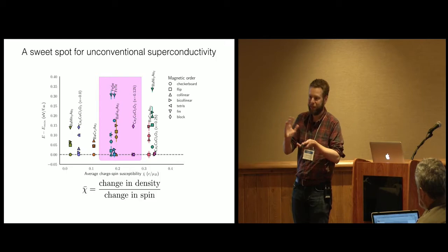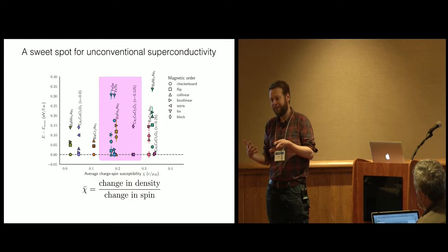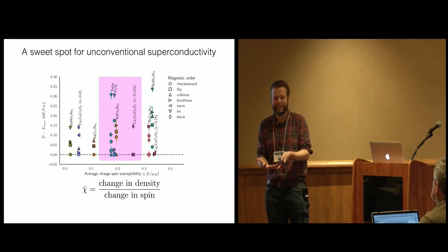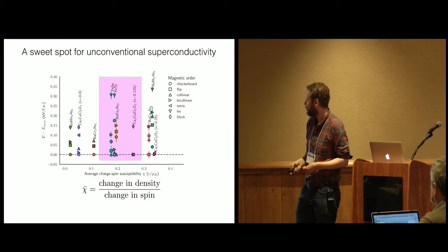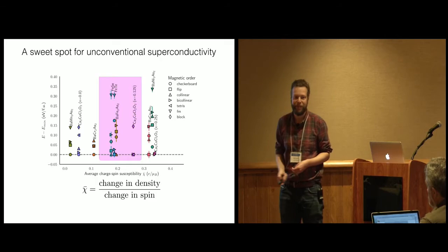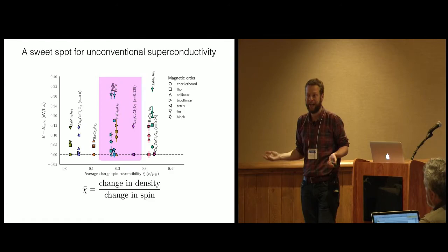And so what we did was we figured out, basically, you look at the change of electron density divided by the change in the spin and the magnetic moments. And what you find is all the superconductors lay in this pink region, which is kind of a happy medium, when it's not too strong. Because think about, if you're trying to ride a wake and the boat's interaction with the water is too strong, the boat is sinking. So that's bad. So these are kind of sinking. These are too bad. And these are too weak. So you kind of want a medium interaction to make a nice wake so you can kind of go along it. And there are other criteria as well that you can get into. But we basically found a nice little happy medium for these materials. And we know we had to do a bunch of calculations. We have one, two, three, four, five, six, seven, eight, nine, 10, 11. We had 12 different materials that we looked at with this very high accuracy method, which hasn't ever been done before. And so that was really useful.